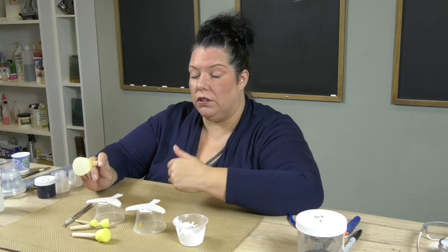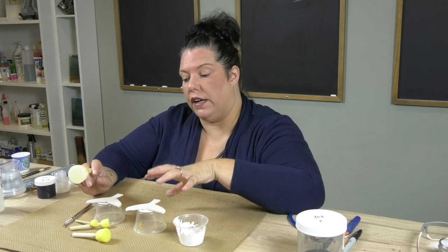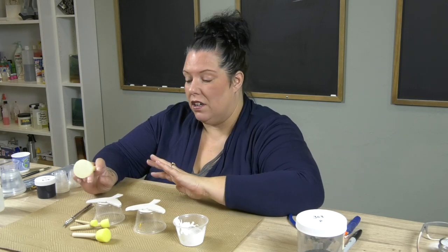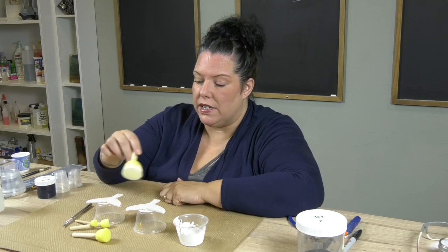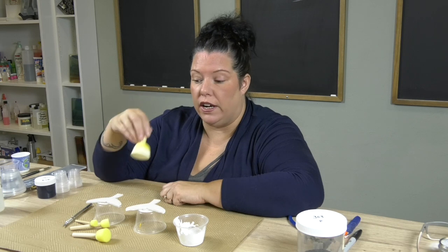Now, you might be thinking from my other videos, I taught you that when you're laying color on top of color, to go ahead and sinter these. That means you put your first base color down, you go into the kiln, and you fire the enamel between 1100 and 1250 just to make that color permanent. You don't have to do that with this. Remember, we're going for 1 firing, okay? So what I'm going to do is have my base color down, and I'm going to take a blow dryer to it. Takes maybe 2 minutes, and then I'm going to add more color on top, staying within the 1 firing theory. So let's go ahead and blow dry these, and then we'll start adding some of that custom color.